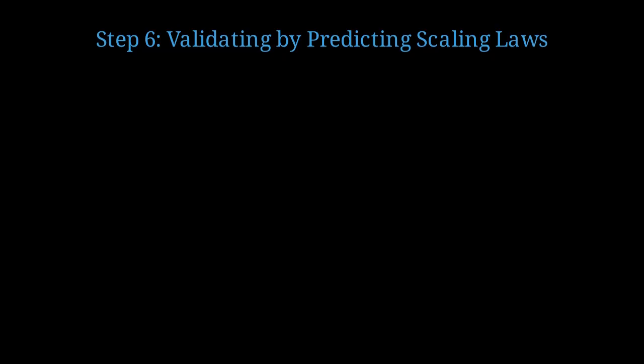The fitting procedure is straightforward. We measure the GMR ratio from our resistance versus field curves, then invert the formula to extract beta. This tells us the degree of spin asymmetry in our materials. Step 6 is the critical validation step. A good model must predict how GMR scales with structural parameters like layer thickness and interface quality. This is where theory meets engineering.